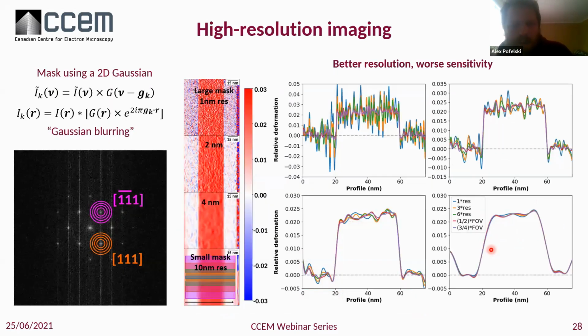So one comment here about this GPA is something particular to GPA: the link between the mask that you use and the noise that you get in your final results. If we go very simple, it's actually not very accurate what I'm saying here, but just to go very easy, when we do a Gaussian masking around the reflection, we multiply by a Gaussian function. If we come back to real space, then this product becomes a convolution. So as a first approximation, what we're doing with this Gaussian mask is a Gaussian blurring of the image in real space.